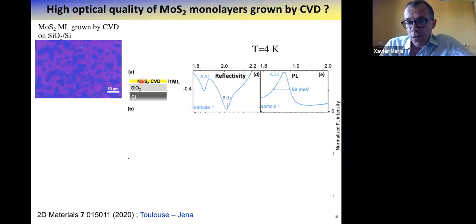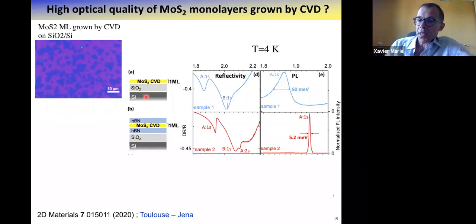What we have done is that we have removed this monolayer and transferred it to a targeted substrate, another substrate, where we have already transferred a HBN layer. Very flat, very clean. So we have now this MoS2 CVD monolayer on HBN, and on top of that, we protect the MoS2 monolayer by a top HBN. And here, the improvement is spectacular.